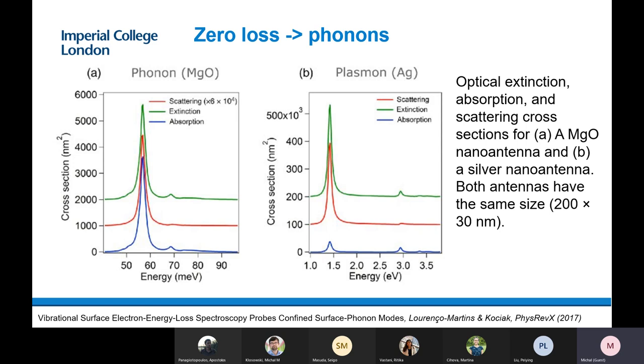Moving to more applied experimental things, we can observe phonons. Here on the left-hand side image we are recording peaks at millielectron volts — very, very small electron losses can be recorded. This is reflective of phonons: we are recording oscillations of the ions of the crystal lattice, very small vibrations, and we can relate those vibrations to optical properties of the sample. This type of experiment cannot really be done on the systems we have at Imperial — you will have to go to something like SuperSTEM to perform these experiments.